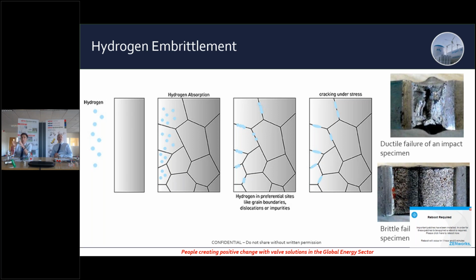And the two images on the right of your screen there, one being a ductile impact specimen, when it was subjected to an impact load, there'll be a certain amount of stretch in the material, to put it in basic terms, before it fractures. The material underneath, very brittle fracture. That image is quite characteristic of almost like a cast iron breaking. There's no give, it just ultimately fails at quite a low impact strength. And that's really the challenge of material selection. Hydrogen can cause a material to behave in quite a brittle manner.